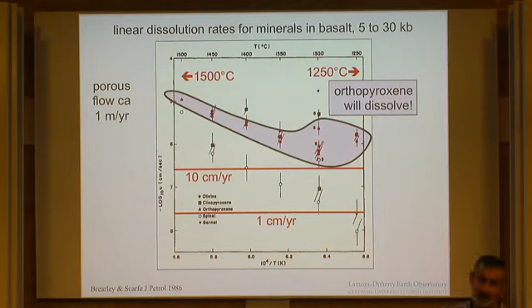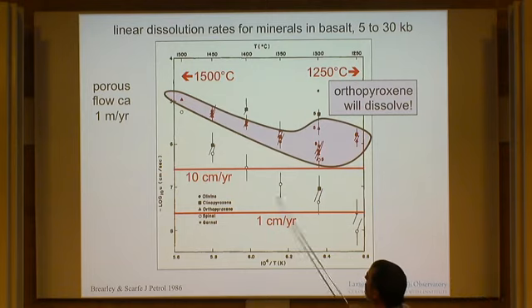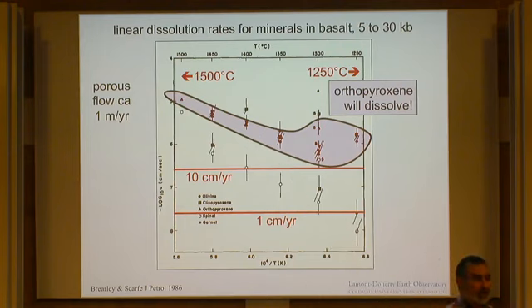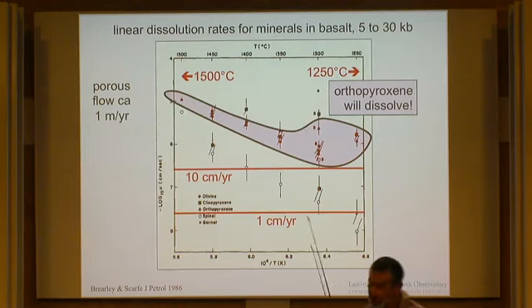The crystal size might be 1 centimeter, and the rates of dissolution are very much larger than the diameters of the crystals. So there's really no way that porous flow could bypass the orthopyroxene crystals in the mantle and allow the melt to diverge from equilibrium with pyroxenes. So it would be andesitic if it all rose by porous flow through an orthopyroxene-bearing peridotite.